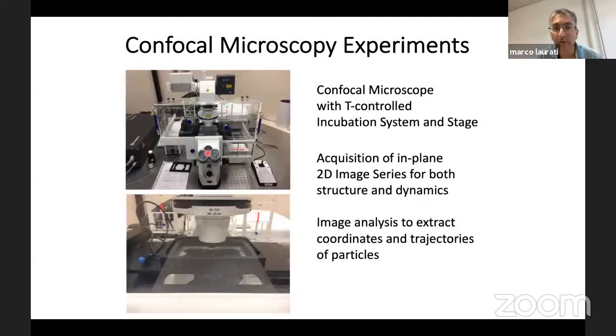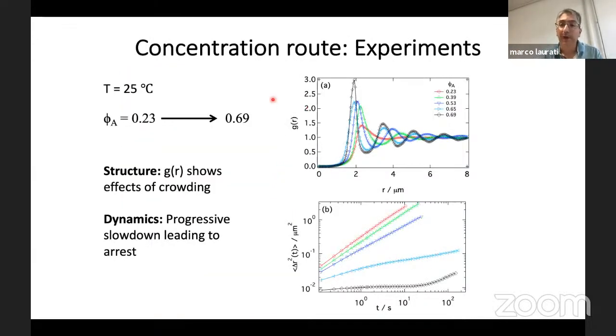For this, we did confocal microscopy experiments and particle tracking, in this case essentially in plane, in 2 dimensions. And from the particle tracking experiments, we first investigated the transition at the temperature of 25 degrees, increasing the number density of the particles from a small value in the fluid state to a value in the glass state. And we could calculate the pair distribution function, which shows what you would expect: the maximum of the g(r) is shifting to smaller values while increasing the packing, and also the peak, of course, grows. And in the dynamics, we could see the classical slowdown until essentially we reach the dynamical arrest in this case.